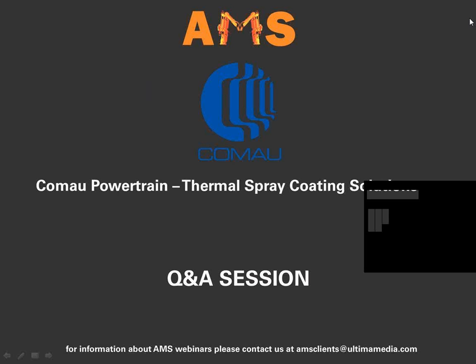Thanks, Paolo. Next question, what's the minimum bore diameter possible for applying the thermal spray? The current torch design from Flame Spray that we've been using is capable down to 67. I'd prefer to stay not much below 70. Once the package starts to get a little tighter, it's a little hard to fit in. However, Flame Spray has developed what they call a mini torch, and it gives them the ability to get down to approximately 37 millimeters.